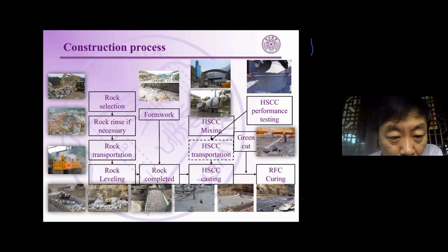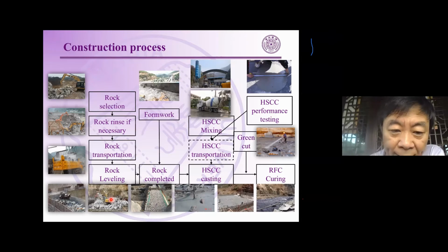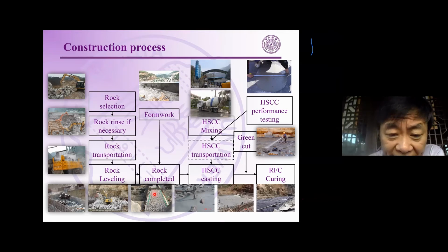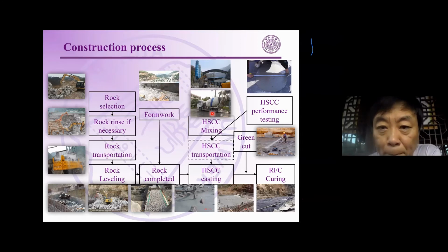And then you can transfer them into the lift, and you can use the excavator to help with rock leveling. The leveling is to maintain a similar thickness or height of the lift, about 1.5 meters to 3 meters. And of course, we can install some formwork. And then after the rock placement is complete, we can use a mixing plant to make the high performance self-compacting concrete and cast it into the lift.